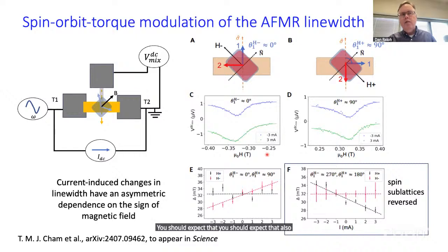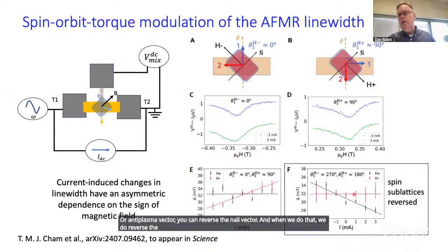Now, within this picture, if you can reverse the direction of the Néel vector, you should expect that to also reverse what sign of magnetic field gives you a strong dependence of the line width on current. And in fact, that is possible to do. There's a little bit of asymmetry in the magnetization of the two layers, and so by applying a large magnetic field parallel or anti-parallel to the Néel vector, you can reverse the Néel vector. When we do that, we do reverse the sign of the magnetic field that gives us a strong dependence of the line width on current. That's just because by reversing the spin sublattices, we've reversed the sign of the magnetic field that aligns the first spin sublattice with the spin orbit torque direction.